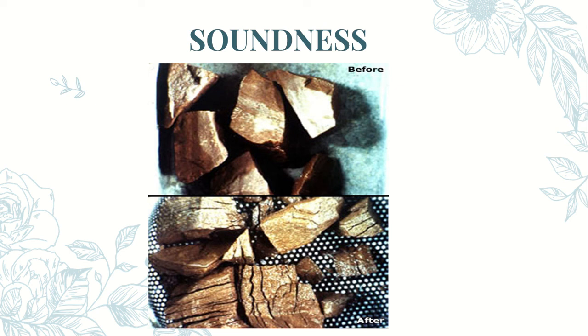After a specified number of submerging and drying repetitions, the aggregate is sieved to determine the percentage loss of the material. The formation of salt crystals is supposed to simulate the formation of ice crystals in the field and could therefore be used as a surrogate to predict an aggregate's freeze and thaw performance. So you can see in the diagram the aggregate before and after performing the soundness test.